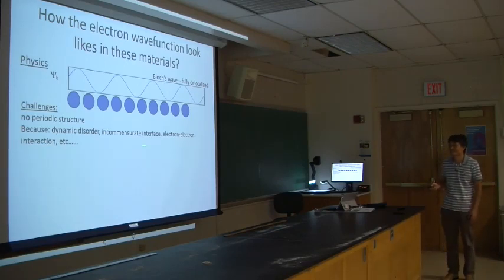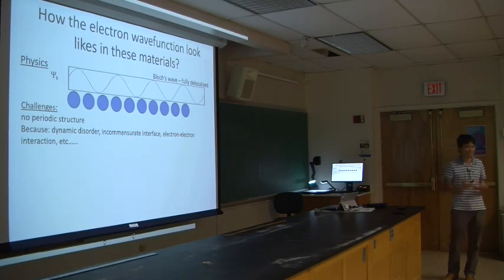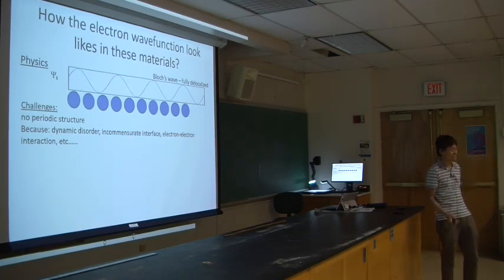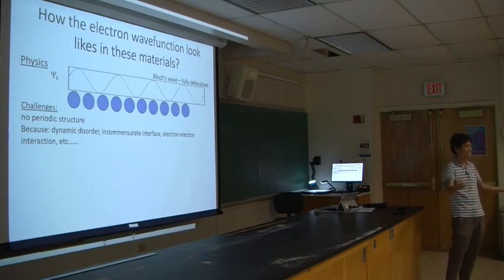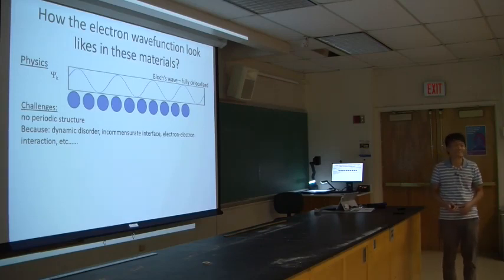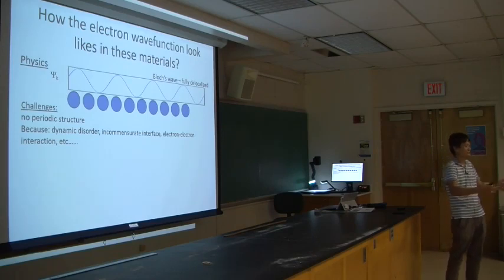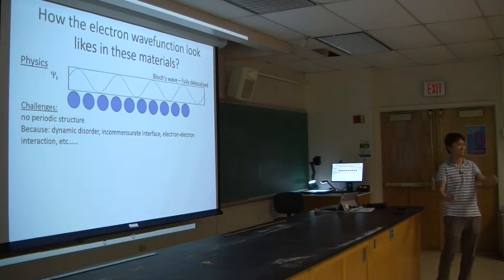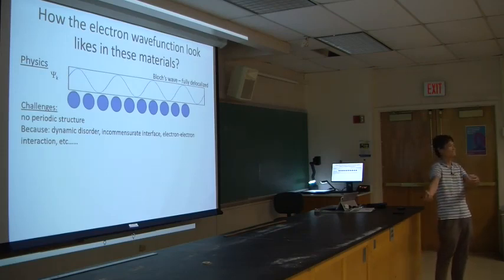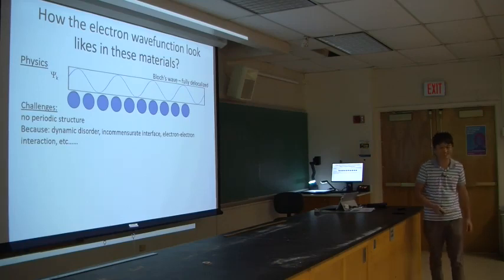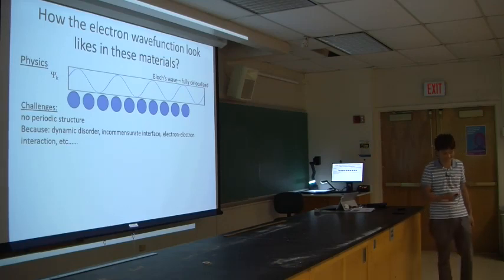Of course, in other cases, for example, when we study interfaces, usually the two materials have different lattice parameters, right? So the lattice cannot match. In these cases, again, you don't have this perfect periodicity, right? And of course, there is electron-electron interaction, such as an electron and hole interacting with another localized carrier. So of course, you no longer have these periodic boundary conditions, right?